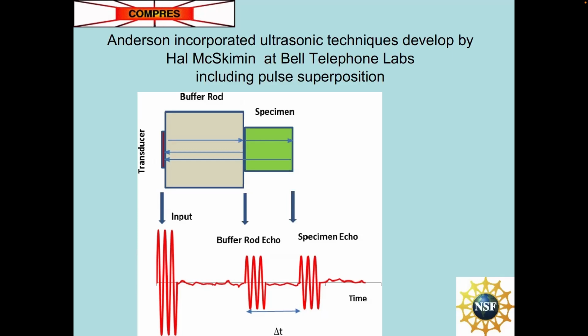So you have, as you look at it on the oscilloscope, a series of echoes: the input signal, the echo from the buffer rod, the echo from the specimen, and of course the difference between these two tells you the travel time in the specimen itself. It doesn't tell you the velocity, it tells you the travel time. The next slide